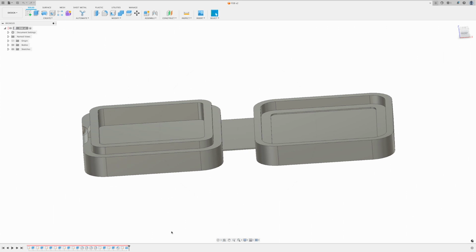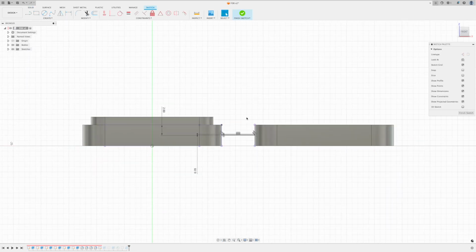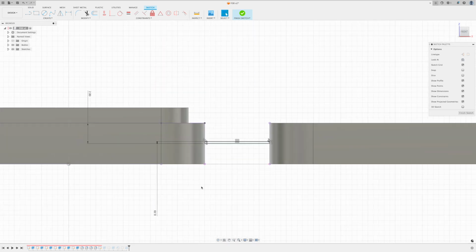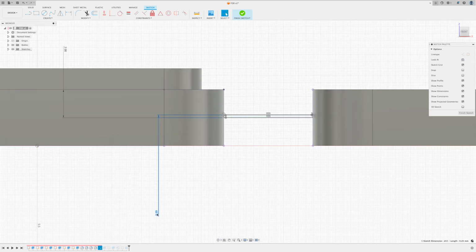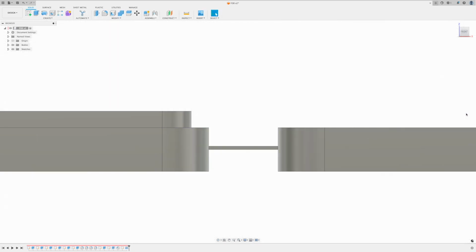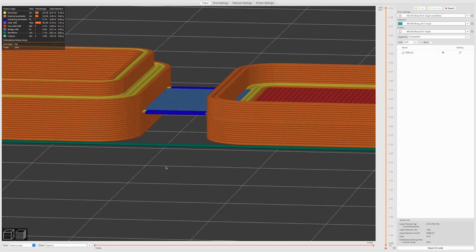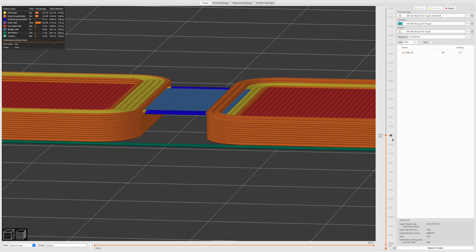So to eliminate the gaps, we will need to do several things. First, we'll increase the nominal thickness to 0.3 millimeters in the model. This will make the nominal dimension closer to the actual dimension when we print the part. So going back to Prusa Slicer, let's slice the updated model. And we'll double check the hinge thickness using the slider, and unfortunately it's still 0.2 millimeters. So we changed the thickness in the model, but it had no impact on the sliced part.